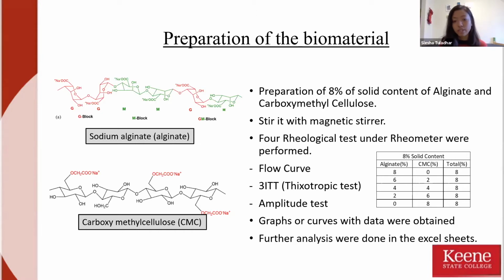Then we mixed it together. We stirred it with a magnetic stirrer until it was a homogeneous mixture. Going further, we did 4 rheological tests under the rheometer, namely the flow curve, thixotropic test, amplitude test, and frequency test. After doing that, the software produces a lot of graphs and curves that were very helpful to further predict how they are going to behave. And then the further analysis was done in the Excel sheet, which is more like compare and contrast, or even getting the average of how the multiple numbers of experiments turned out to be.